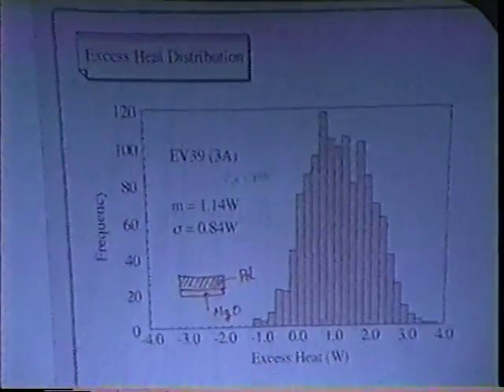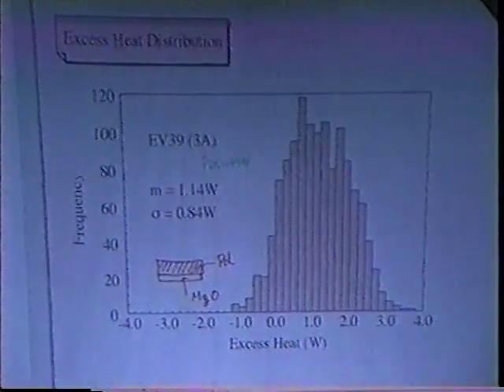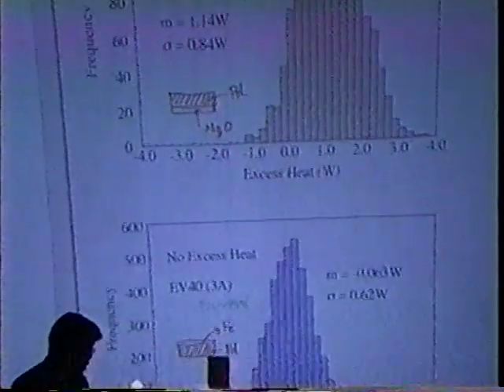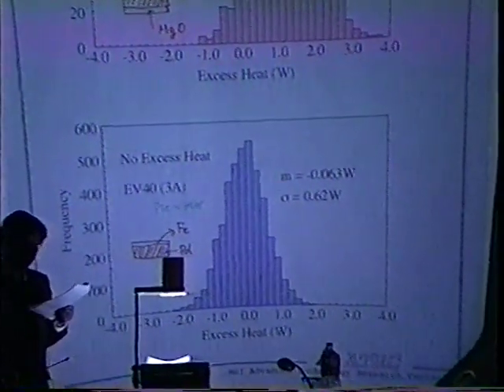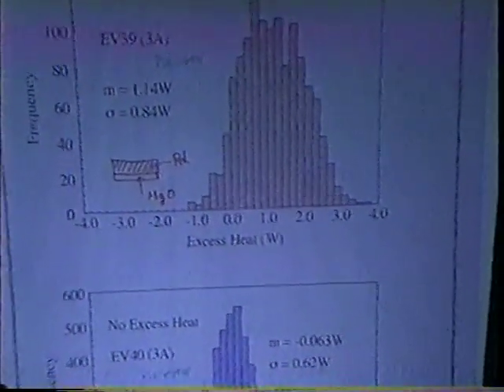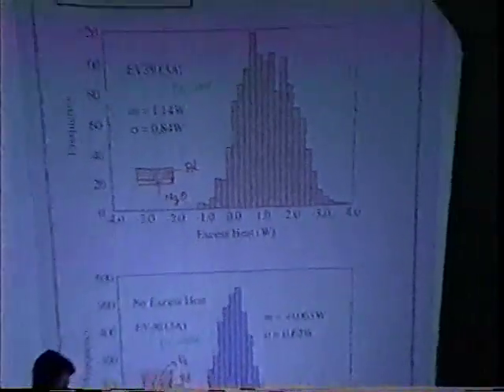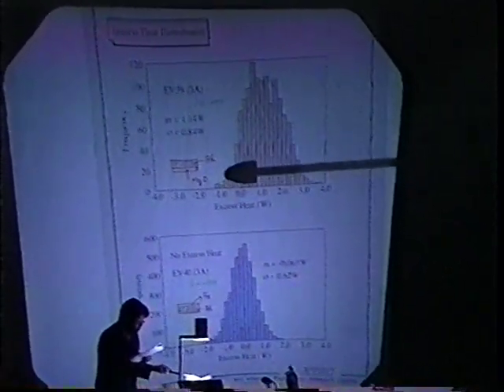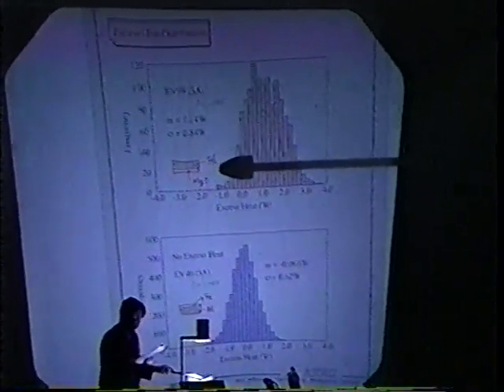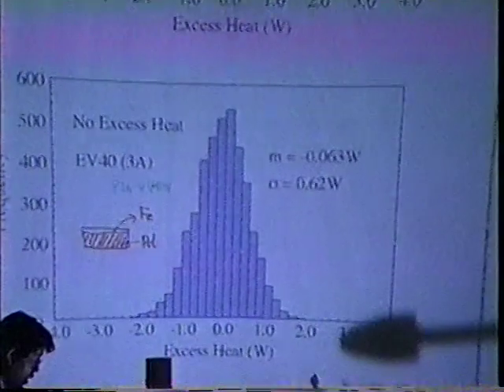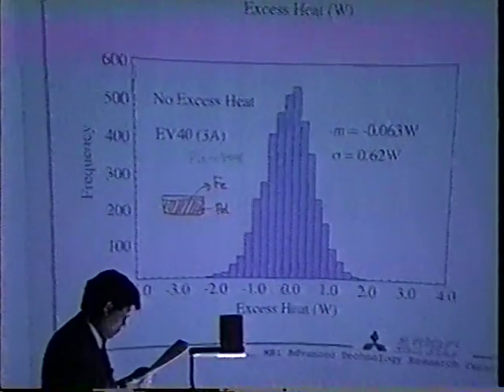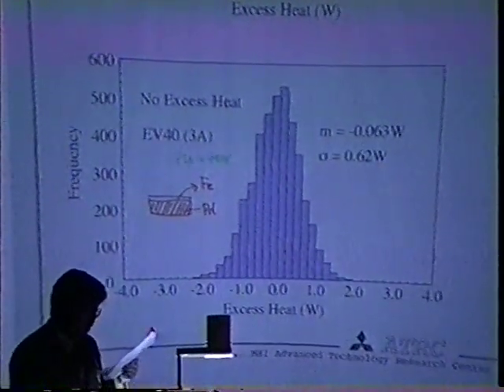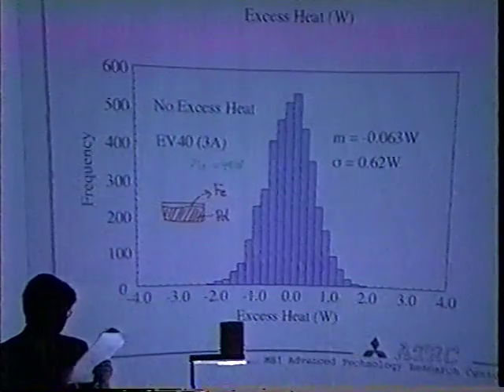These histograms show the comparison of the heat distribution between excess heat and no excess heat. In both cases, input current is 3 ampere, and total input power is about 40 watt. The difference of these cases is the sample treatment. EV39 has a thin film of MgO on the vacuum side of palladium, and EV40 has a thin film of Fe ion on the electrolyte side of palladium. It can be seen that mean value and deviation of excess heat of EV39 is larger than those of EV40.